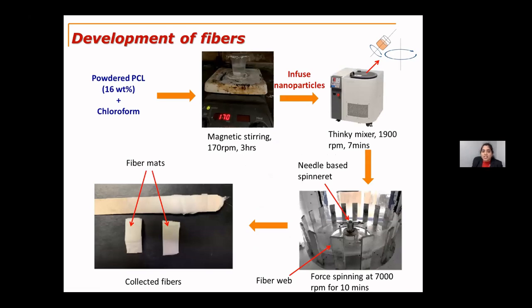So now coming to the development of the polymer fibers. First, we chose polycaprolactone and chloroform. We mix them together. Polycaprolactone is considered as 16 weight percent. That means for 100 grams of solution, we choose 16 grams of polycaprolactone and 84 grams of chloroform, which together makes 100 grams of solution.